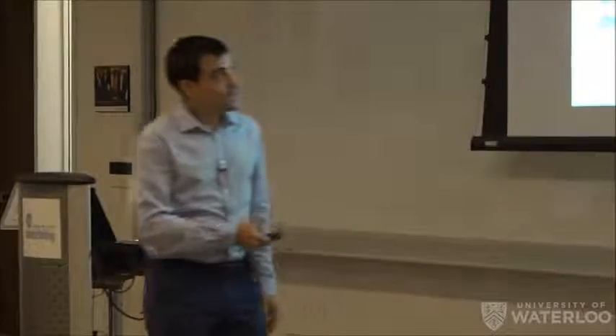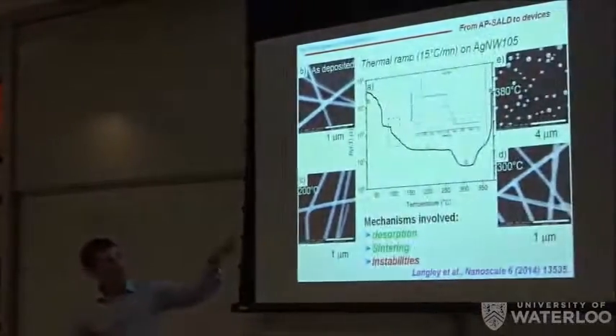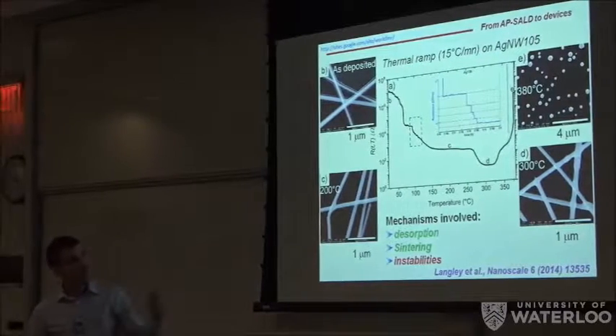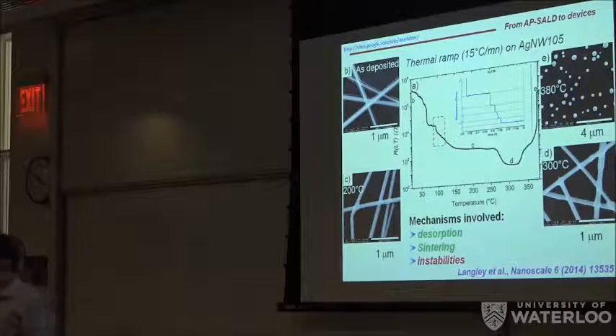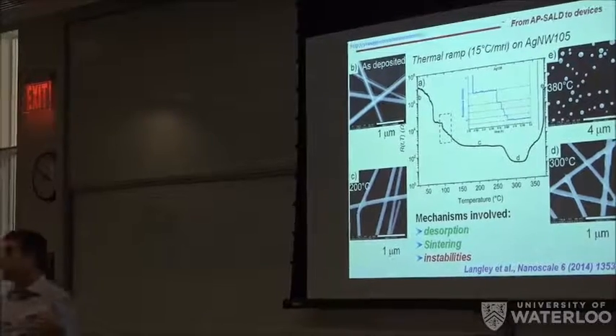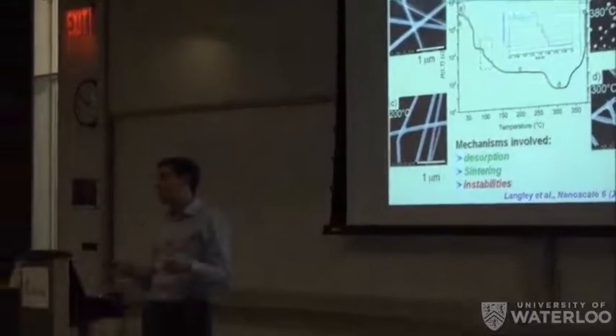Thanks for your presentation. Can you explain more about the coating of silver nanowires? What is the effect of this coating? When you anneal the nanowires, or try to pass too much current, the temperature increases, and then you get the Rayleigh instability. They spheroidize, so you lose the electrical contact. Your network is not conducting anymore.